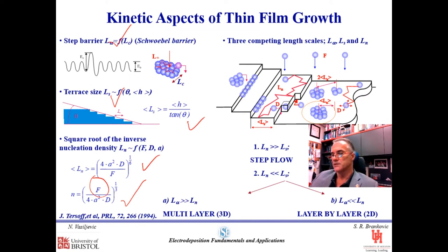In the first case, when we have L sub n much larger than L sub s, that means that the terraces are really short and the probability of nucleation is very low, and most of the atoms that land on the terraces will diffuse to the steps, so we will have a stable step flow growth.